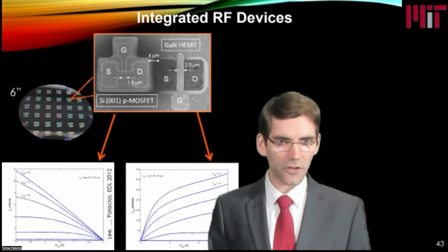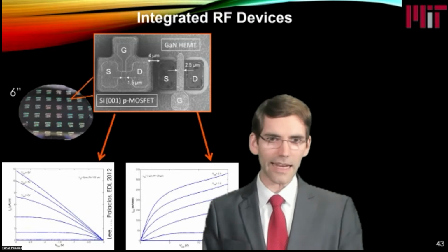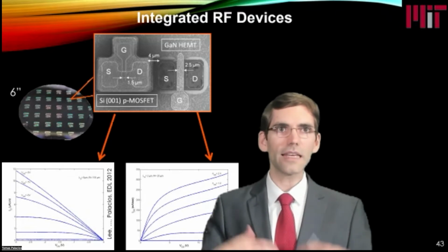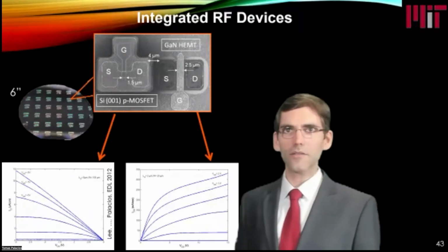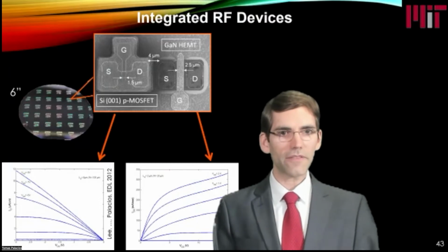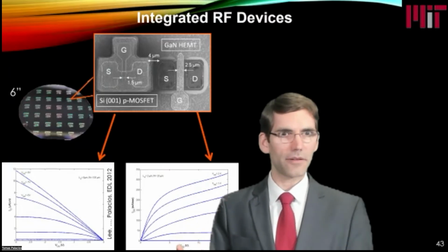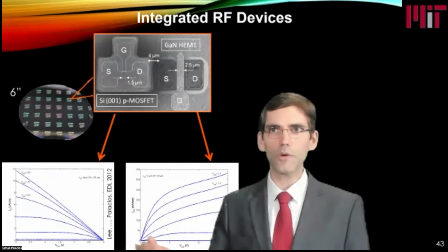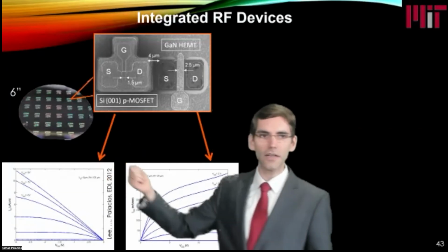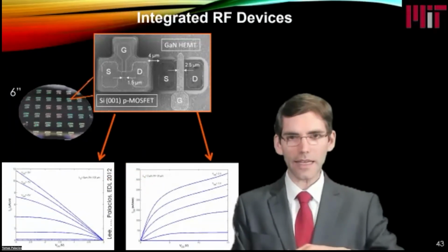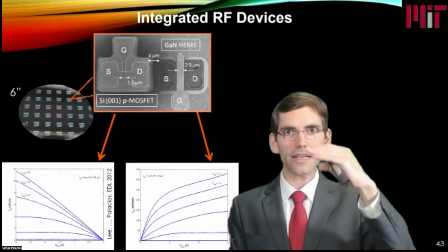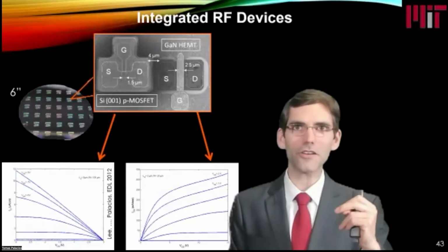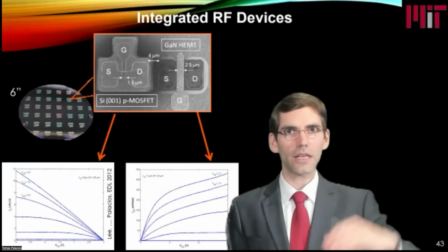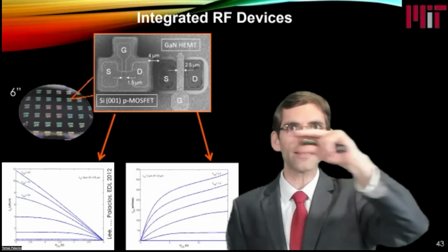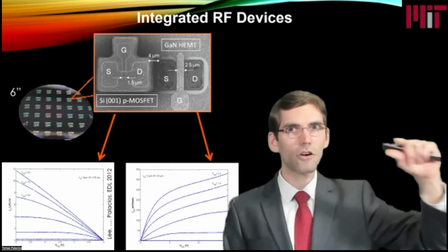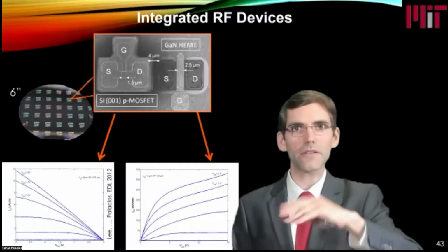So one approach is, of course, to bring silicon transistors and gallium nitride transistors close to each other to build integrated heterogeneous systems. And we demonstrated this a few years ago, where we fabricated gallium nitride electronics right next to silicon CMOS electronics. And we demonstrated this on a 6-inch wafer. And the way we did this was by building an SOI wafer, a silicon on insulator wafer. But in this case, the insulator happened to be gallium nitride. And in that way, we have a silicon active layer where we build silicon CMOS devices, then a thin oxide, and then gallium nitride wafer underneath.